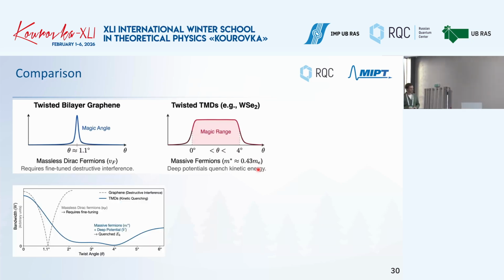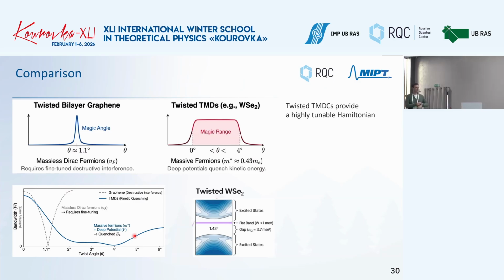unique properties. Here's some comparison in another regime. This is the dependence of the bandwidth on the twist angle. So with a larger twist angle, you can obtain these values. And it turns out that TMDCs provide a highly tunable Hamiltonian. For twisted WSe2, you see the flat bandwidth is below 1 millielectron volt, while the gap is around 3.7 millielectron volts. Okay, I move forward. So I mentioned here that twisted TMDCs provide a highly tunable Hamiltonian.